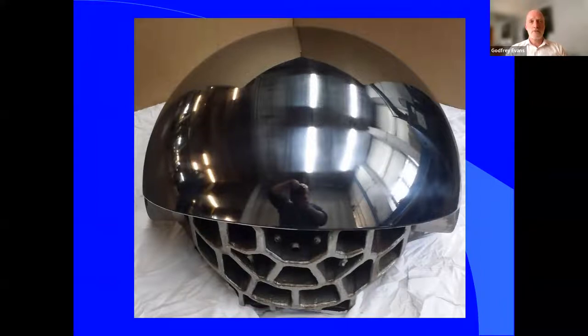And this smooth surface is laid down onto a high percentage nickel casting, which in its own right would wear away very, very quickly. The coating that's applied is between 25 and 50 microns. That's 1 to 2 thousandths of an inch for the older viewers. And that's sufficient to make this ball valve last for many, many years by comparison to a few hours in the uncoated condition.